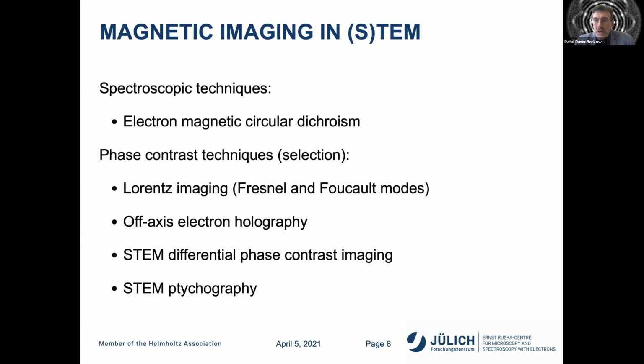The one point I would make is that most phase contrast techniques are applied with the electron microscope objective lens switched off, so that the sample is in magnetic field free conditions, and instead usually a non-immersion lens is used instead, and then magnetic fields can be applied to the sample to study switching processes in situ in the electron microscope.